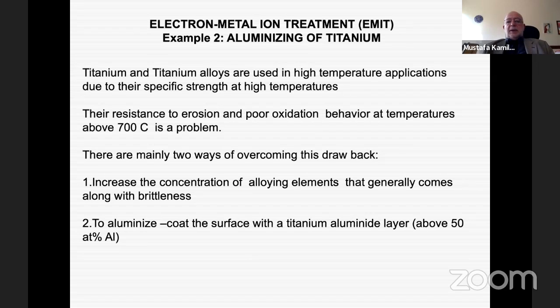As you all know, titanium and its alloys are used in high temperature applications because of their specific strength at high temperatures. However, their erosion and poor oxidation behavior above temperatures of 700 degrees is a problem. So one of the main ways of overcoming this problem is to alloy their surfaces with aluminum, or you can change the alloy composition or produce beta alloys or highly alloyed systems. They are expensive, and also they bring along very high brittleness.